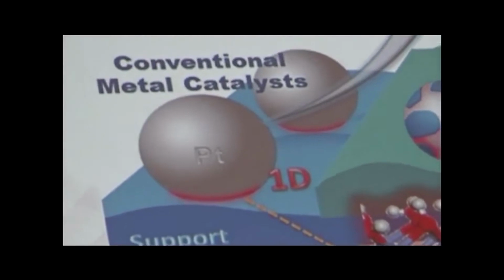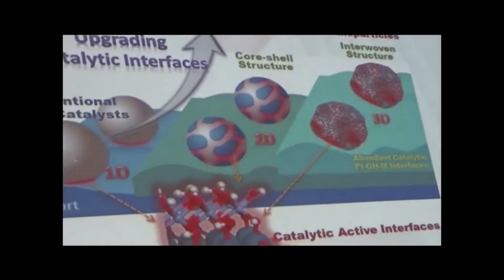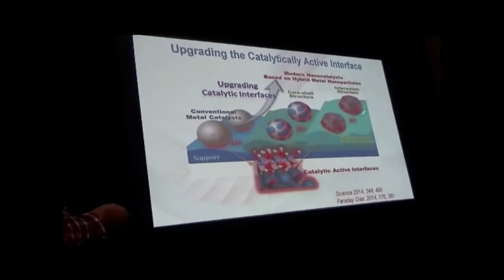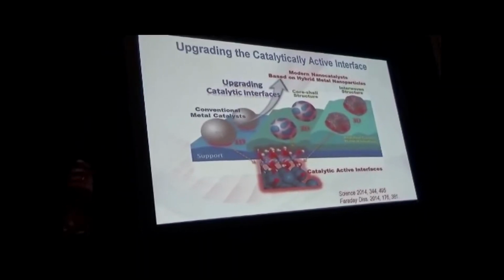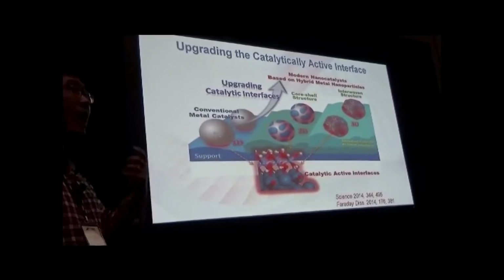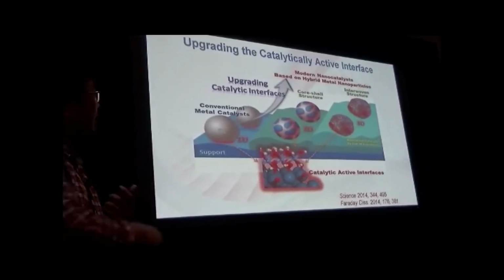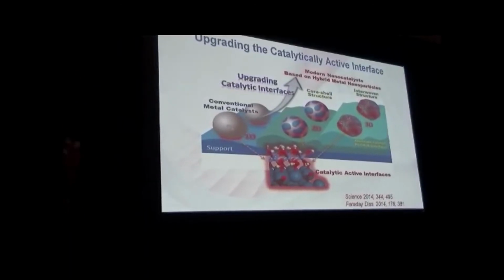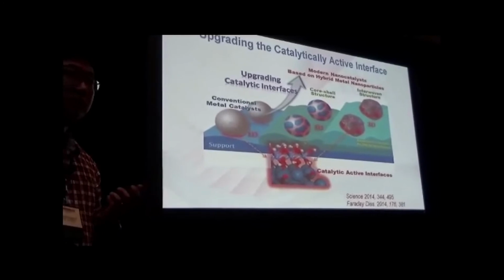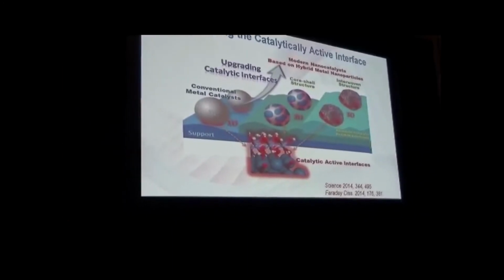Here is our proposal. In the commercial catalysts, the interface is limited. When we grow the iron oxide on a noble metal, we can enrich the interface. And finally, we developed a new strategy. We can synthesize sub-nano alloys of platinum and nickel, and put them in a reaction condition so that we can get a hybrid structure with a 3D interface. Then this one can work for more than 1 month for CO oxidation without any decay. Yes, this paper was published in Science in 2014, and the complete computation work has been published in Physical Review Letters.